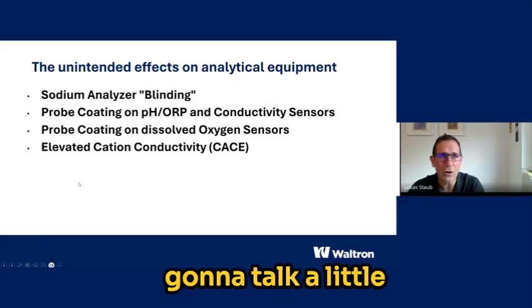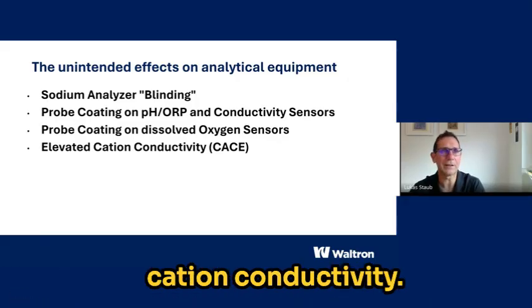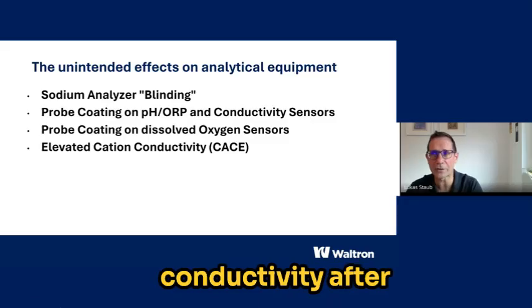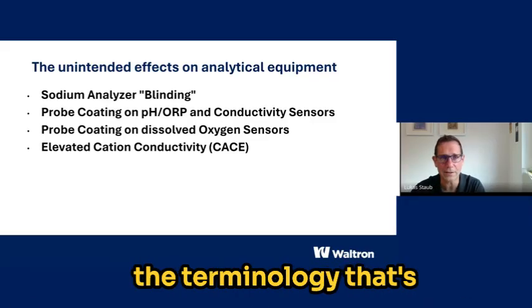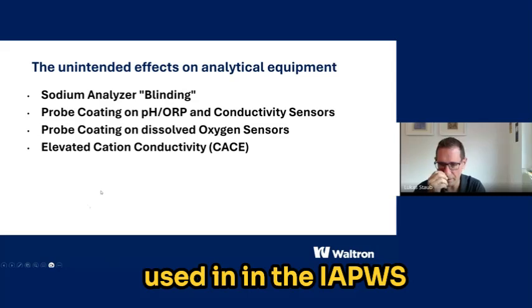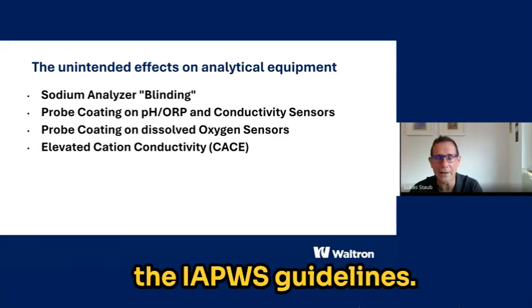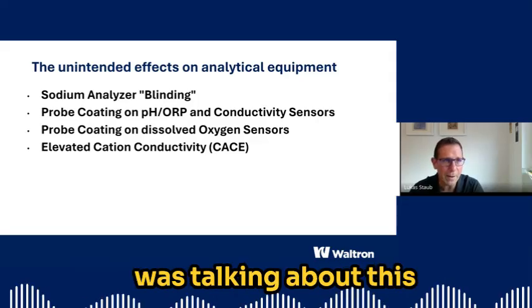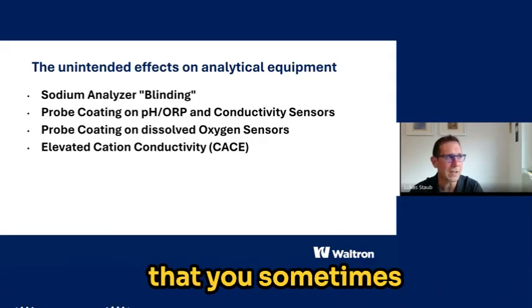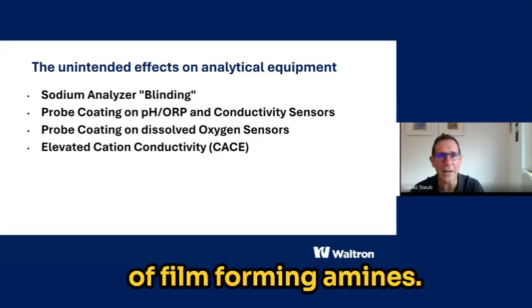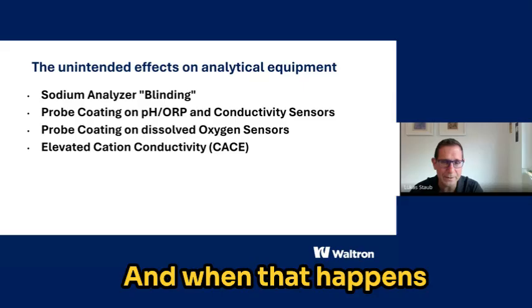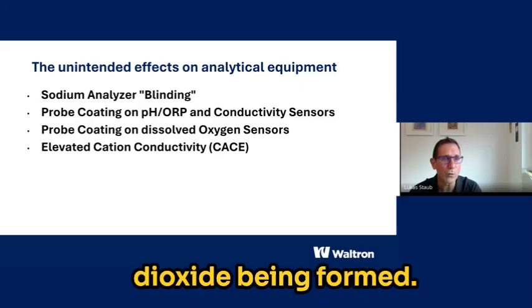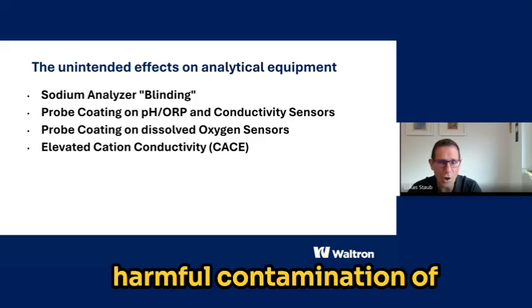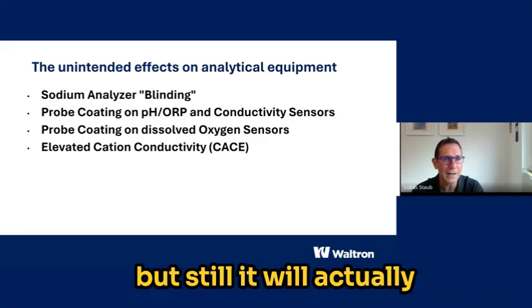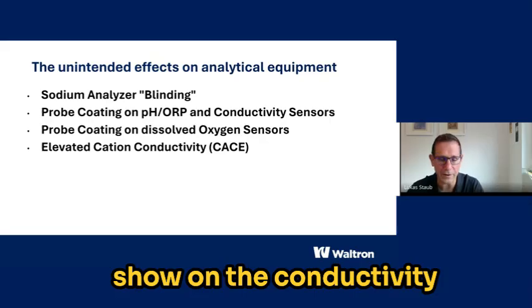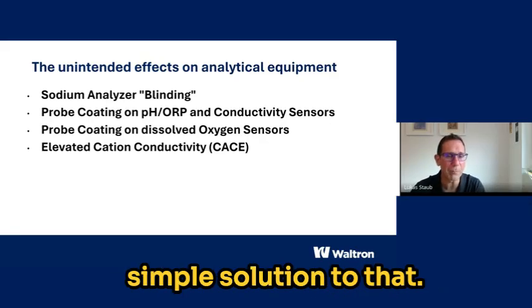Last but not least, I'm going to talk a little bit about elevated cation conductivity. Elevated cation conductivity, or conductivity after cation exchange, that's the terminology that's used in the IAPWS papers, for example, in the IAPWS guidelines. Of course, when I was talking about this decomposition process that you sometimes see in the application of film-forming amines, when that happens, there is also carbon dioxide being formed. Carbon dioxide is not a harmful contamination of your water steam cycle, but still it will actually show on the conductivity after cation exchange. Now, there is a pretty simple solution to that.